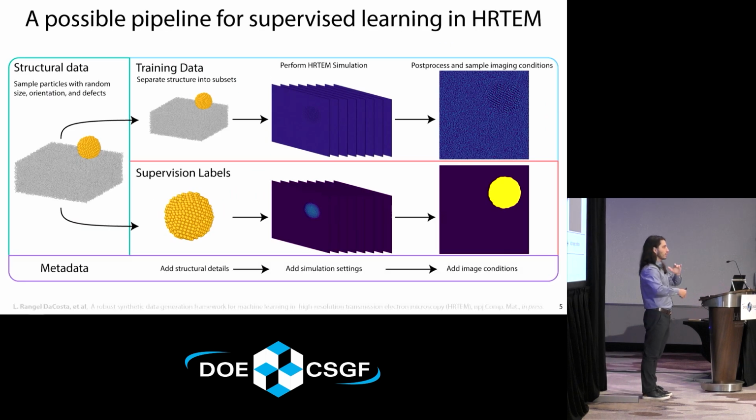One way we can think about making that workflow is if we have access to a structure, we can put it through the simulation and simulate it in two ways, on the substrate or in a realistic sample of interest, and generate an image as in the top right. But since we have access to the structure, we can begin to make supervised labels in a very informed, physics-based and ground truth way. For example, if we wanted to know where that nanoparticle is, a problem in the image space known as image segmentation, we can simulate just a nanoparticle. We can use some physics-based information about where that nanoparticle is. Here, the phase of the electron wave function as it passes through the material, which we can't access experimentally. Then we use that phase to create a threshold and create a mask that is based on how that particle actually looks or should be.